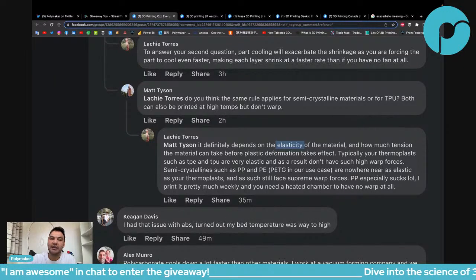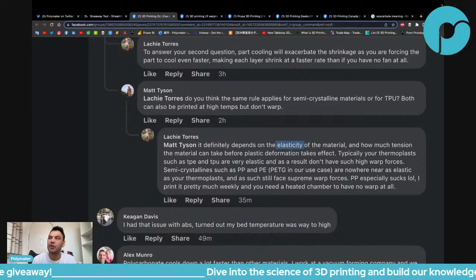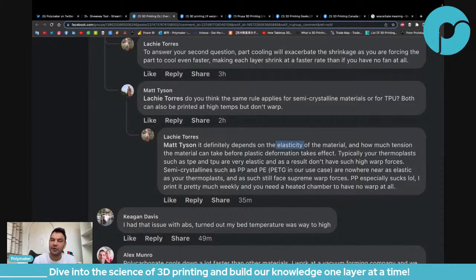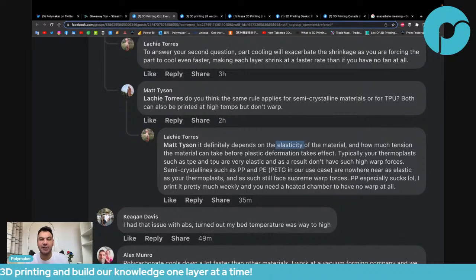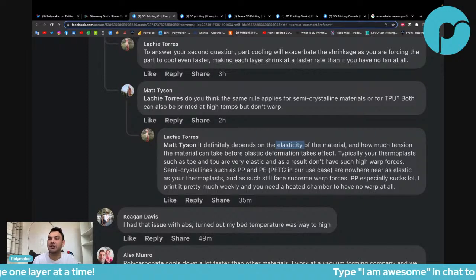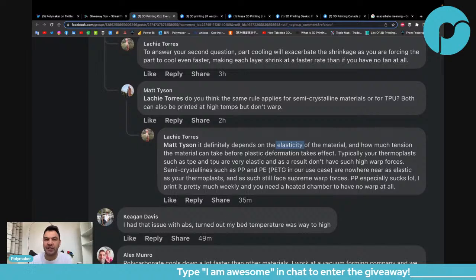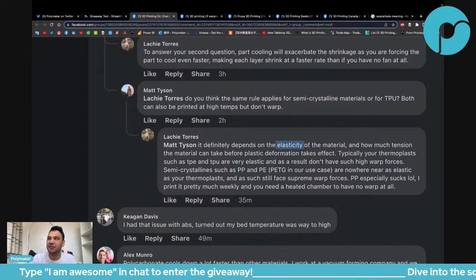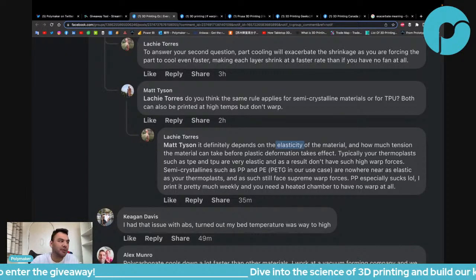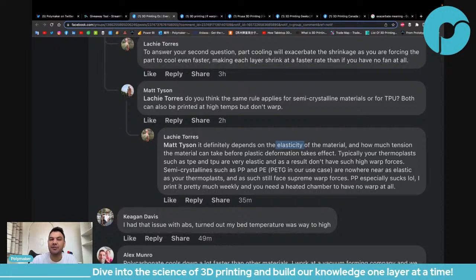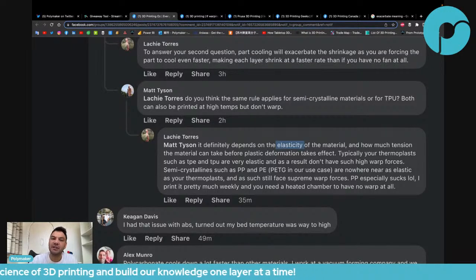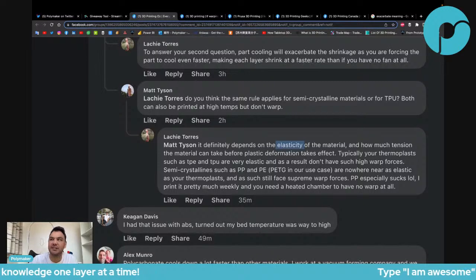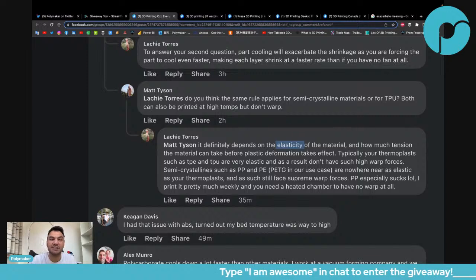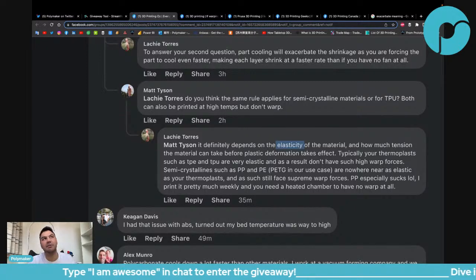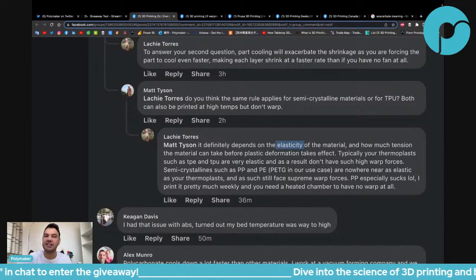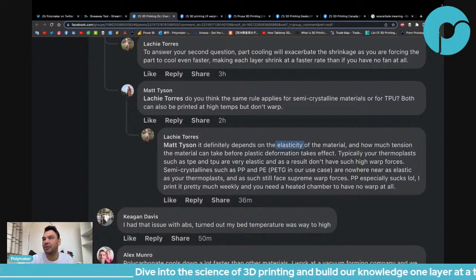Yeah, at least in the elastic shrinkage theory, the goal is that you can maintain the material above Tg or close to Tg long enough so that it can release the stress. So whether you use a cooling fan or not means you allow less time for it to release the stress. If you use 100% cooling fan with a 73-degree chamber temperature, most likely it should warp more than if you don't use the cooling fan, depending on the ABS you are using. Because if you are using ABS Plus, for example, from eSUN, then their Tg is around 75 degrees. I don't know if we call it a fake ABS or a modified ABS, but the fact that the Tg is lower will make it warp less.